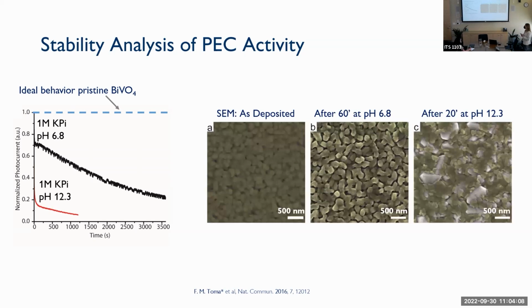And so for me at the time and for my research group, it was a lot about understanding why this material that was reported to be stable in literature, because probably people were just testing it for 1 or 2 minutes while getting the efficiency parameter, was instead not stable. So the very first thing that we did was just looking by scanning electron microscopy at how the material was changing over time. So this was an ex situ analysis that we did.